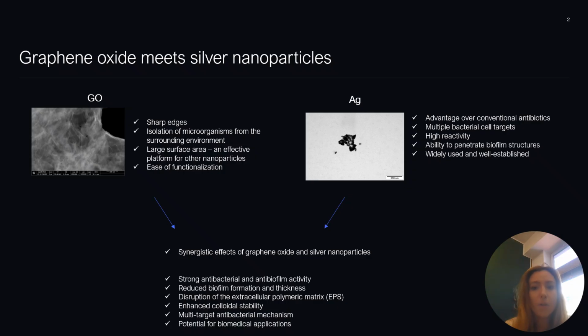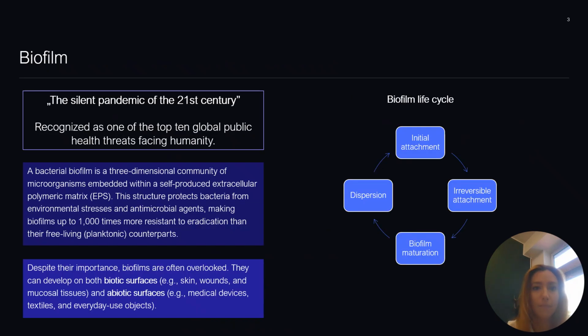Such nanocomposites have been reported to exhibit, for example, strong antibacterial activity, but also reduced biofilm formation and thickness, and disruption of the extracellular polymeric matrix. The graphene oxide platform also exhibits enhanced colloidal stability for the metal nanoparticles. These advantages make graphene oxide and silver nanoparticle nanocomposites promising candidates for the development of next generation antibacterial coatings, including textile materials.